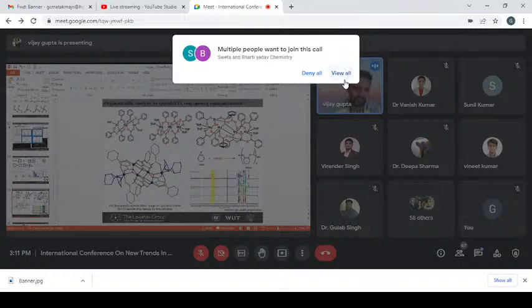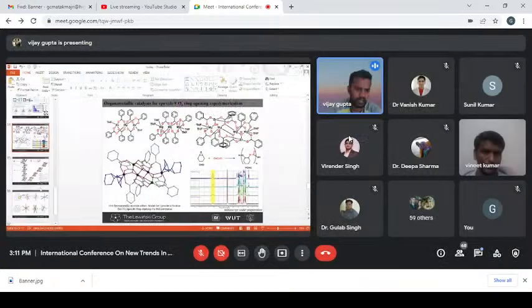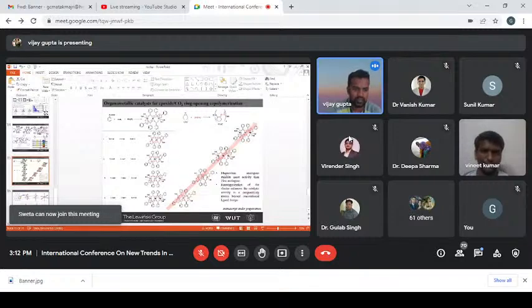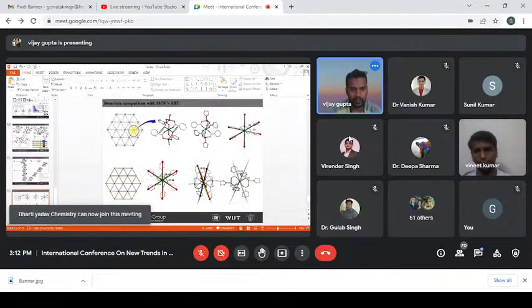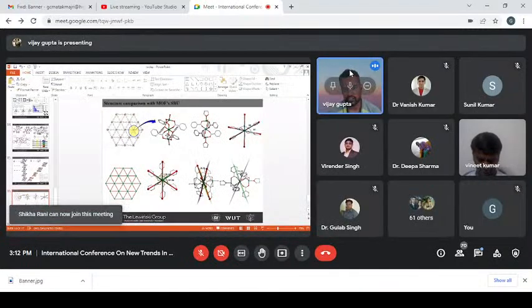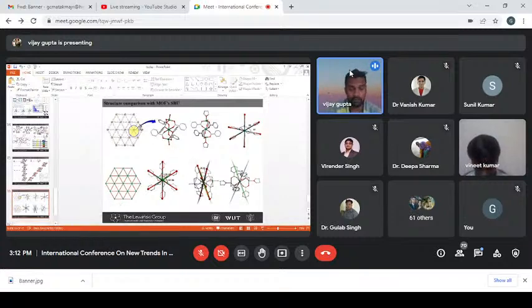And we have also isolated this cyclohexene oxide adduct, which is, I think, the first example where we can isolate this intermediate in the ring opening polymerization reaction. These are more examples we are studying for other applications, and we have compared this kind of building block. This is a known MOF which has a similar building block, and we compared it with our building block and find that it has very similar structures, so we can use our smart strategy to make this kind of framework, which is a mixed metal framework.